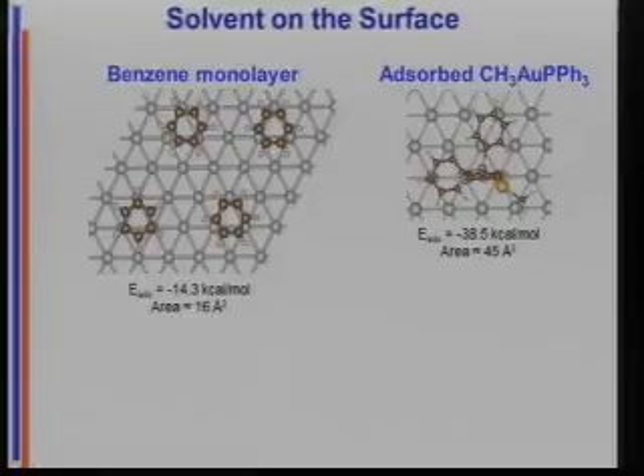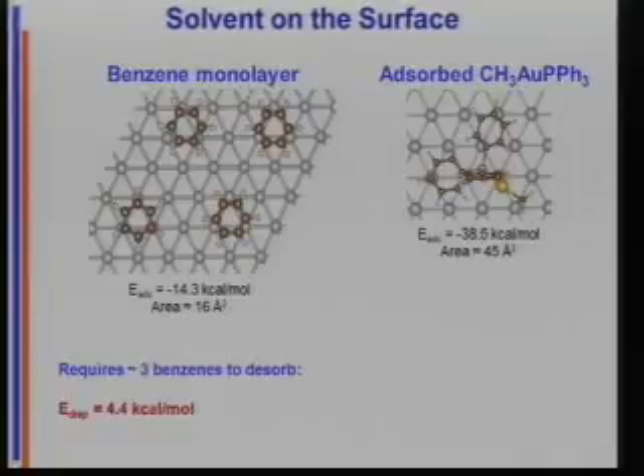So if we start here and we get there, we need to remove 3 benzenes from the surface. You do the math, and you discover that it's 4.4 kcals uphill to desorb the benzene and adsorb the precursor. So that's not what's going on here.